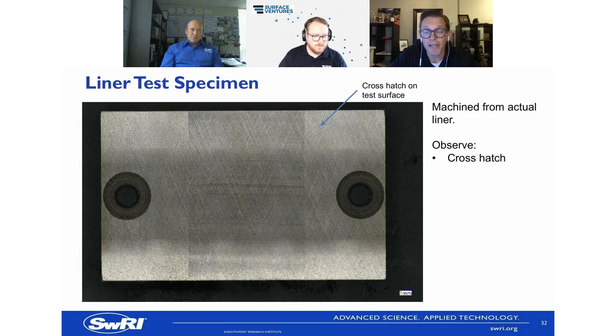From the engine, yes, I do have them. So in micro inches, not microns, the surface finish prior to testing was in the 10 to 12 RPK range, with an RK value in the 35 to 40 range, with an RVK in the 50 to 60 range.